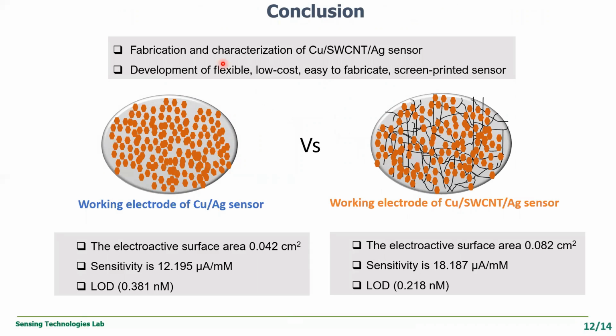To conclude, the fabrication and characterization of this copper CNT silver sensor was done, and we have developed a novel, flexible, low-cost, easy-to-fabricate screen-printed sensor. When comparing this copper silver sensor with this copper CNT silver sensor, you can easily see that the electroactive surface area is increased almost double after incorporating single wall carbon nanotube. The sensitivity is 1.5 times higher, and the LOD, limit of detection, improved. That means it decreased to 0.218 nanomole.